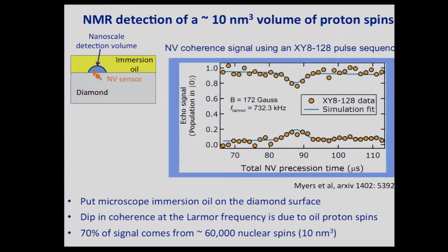The immersion oil has hydrogen spins in it, and those proton spins, in the presence of a magnetic field, as I already alluded to before, are going to feel a torque, and they're going to start precessing around the magnetic field, just like a spinning toy top. They'll spin at a rate that's proportional to the gyromagnetic ratio of the hydrogen in this case, as well as the strength of the magnetic field. And that characteristic frequency produces an oscillating magnetic field at the location of the NV center.